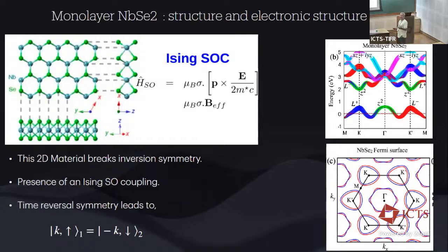What that leads to is that if you want to consider the story of spin-orbit coupling in this system, the generic form of the spin-orbit coupling means that you cannot have an electric field which generates the spin-orbit coupling which is out of the plane. It is primarily in the plane. And the effective magnetic field that this term creates would be out of the plane. Because the momentum of the electrons is also in the plane, the p cross E is going to be out of the plane. And that is going to couple to the spin. What that's going to lead to is that it's going to polarize the spins out of the plane of this monolayer NbSe2 system.